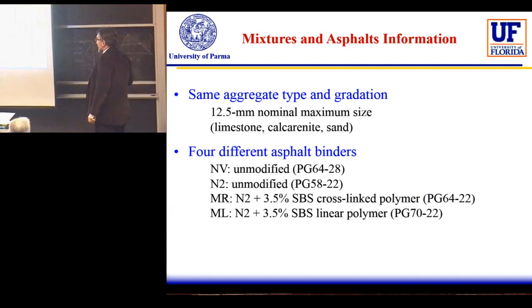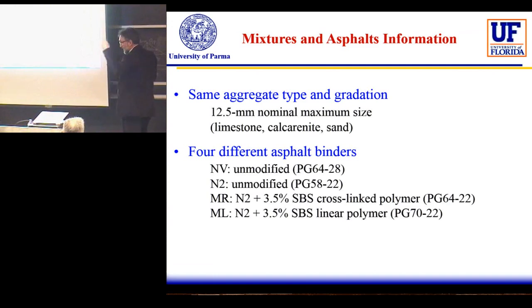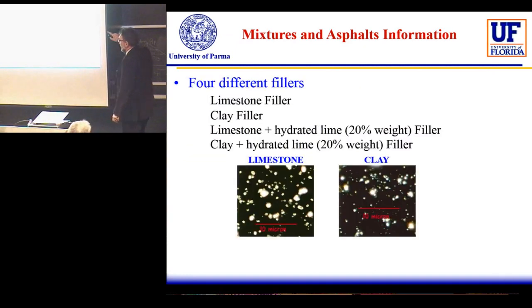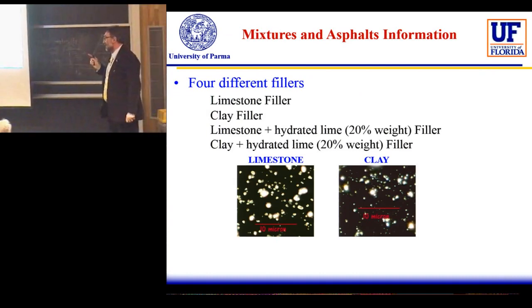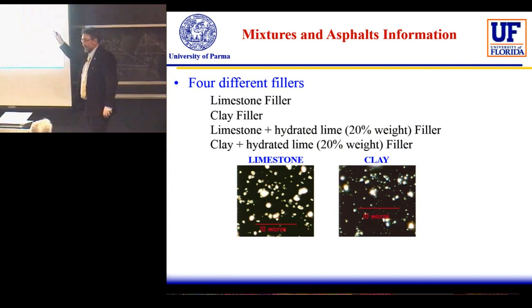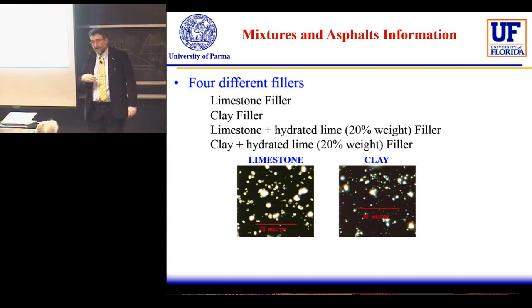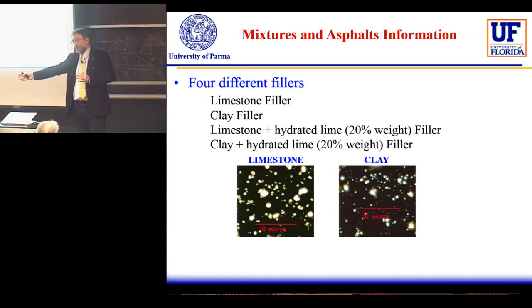To analyze the problem, we used the same mixture as in the other part of the research, and four different binders with different combinations of filler. We used limestone, and this, I have to tell you, is an artificial series of fillers, not fillers always used. In particular, clay is not a traditional filler for the material, but we used it to have something completely different from the mineralogical point of view. So the idea was to have limestone filler, an absolutely mineral-inactive filler, one active filler that is hydrated lime, and clay. So the idea was to have four completely different situations in terms of filler from the mineralogical point of view.